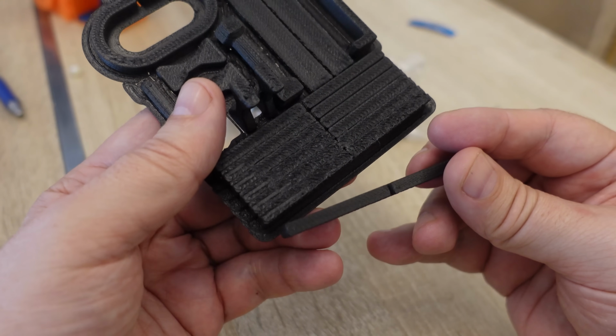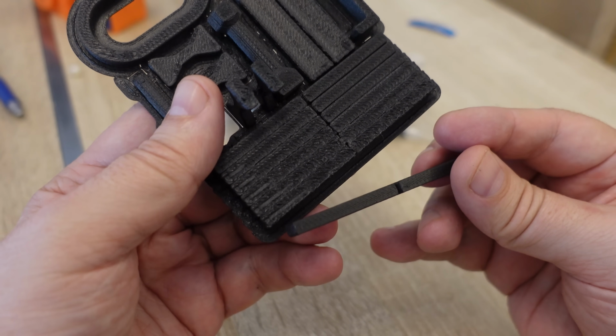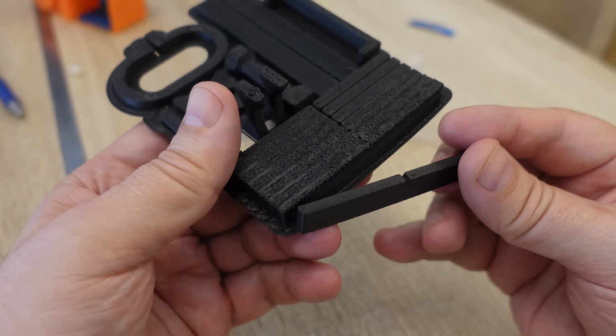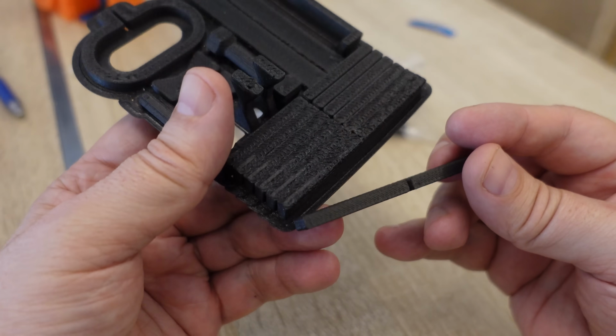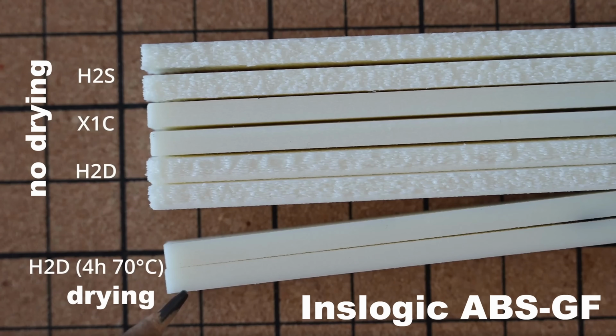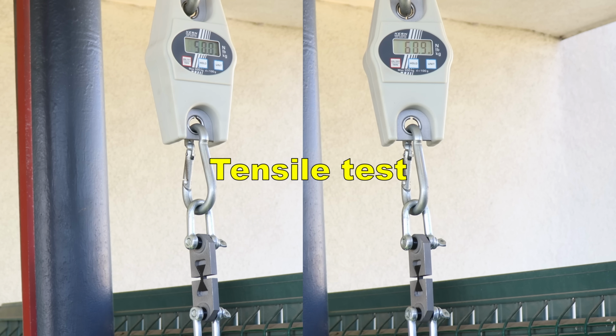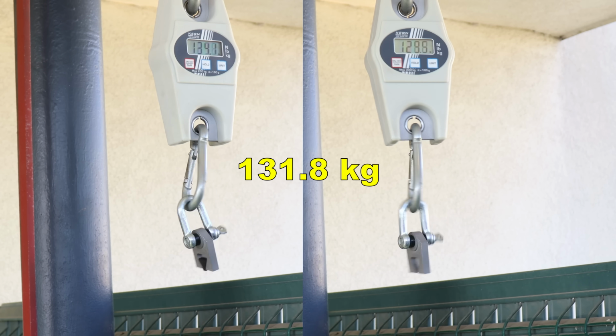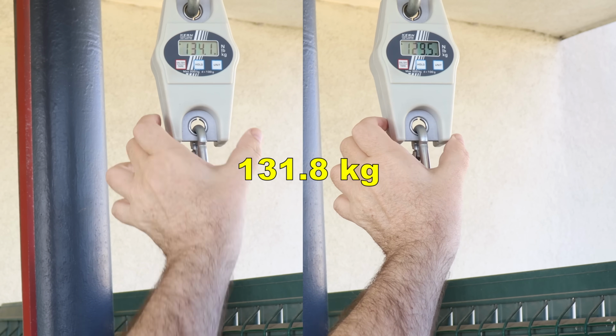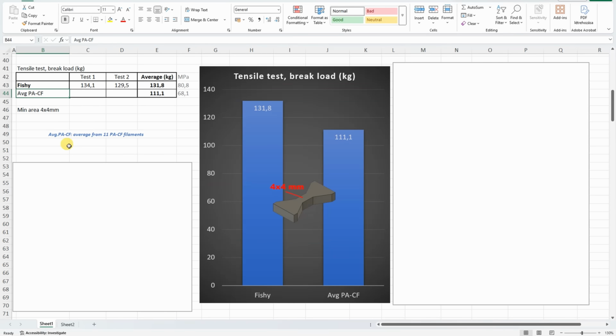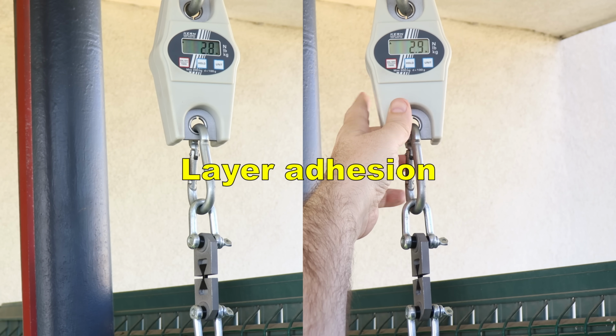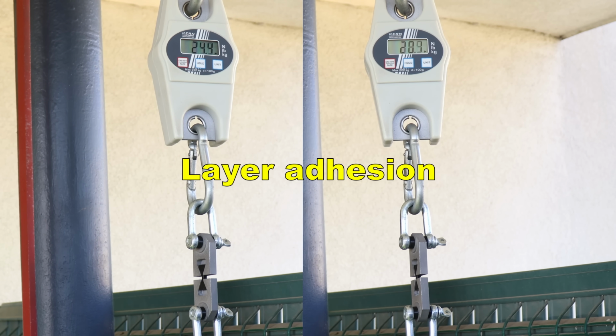Of course, here very important is the fact that H2 printers looks like they are more sensitive to moisture filament compared to X1C, for example. I explained this in one of my earlier videos. Tensile test with horizontally printed objects. Quite strong. For the comparison, I will use the average PA-CF, and I have 11 in that summary table for my Patreon supporters. And these are quite strong numbers, compared not only to the average PA-CF, but almost to any other filament type.